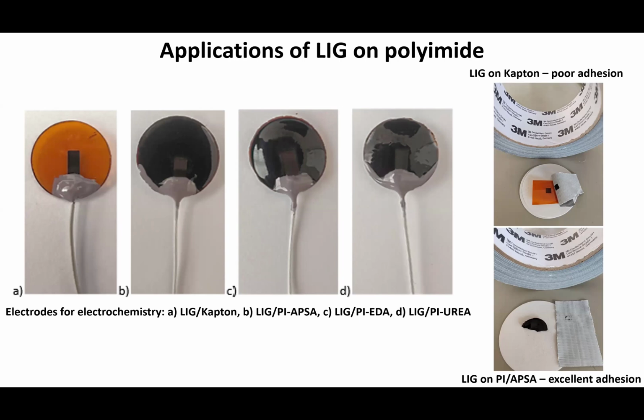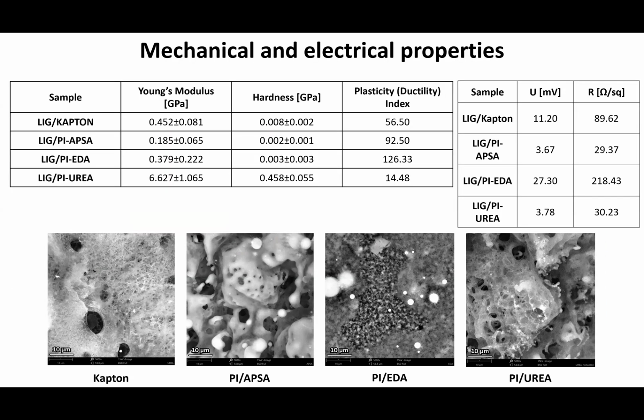I want to show that some of these samples have very good adhesion. For example, on the right top, you see if we put sticky tape on Kapton with LIG, the LIG just comes off, most of it. However, for example, this APSA sample is quite good in the sense that LIG barely comes off, and the sheet resistance changes very little if you attach a strong sticky tape to it and remove it. So the adhesion is great, which is good for applications. We've performed detailed characterization of these samples, including mechanical properties. Well, they're all different. Some of them have lower Young's modulus than Kapton.